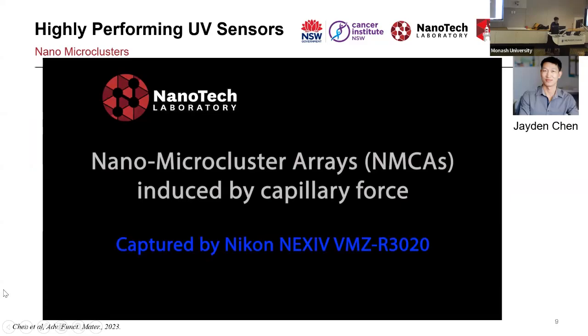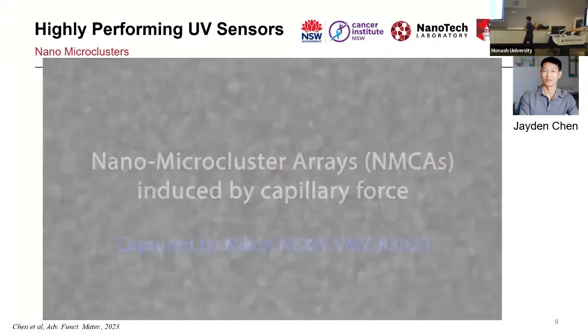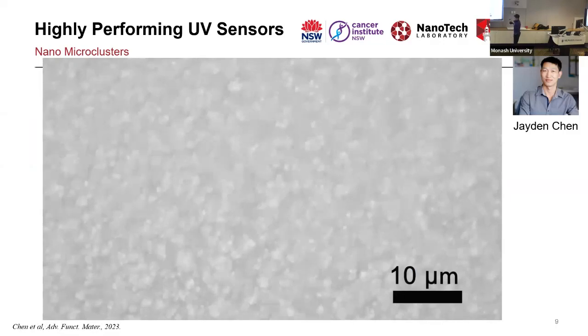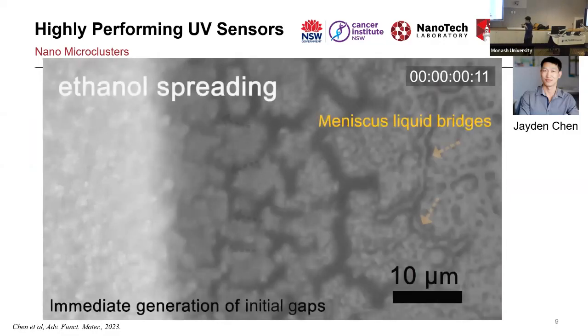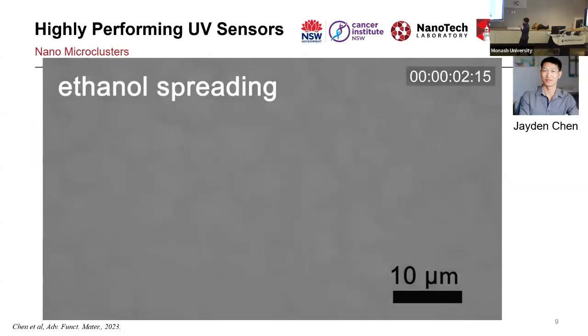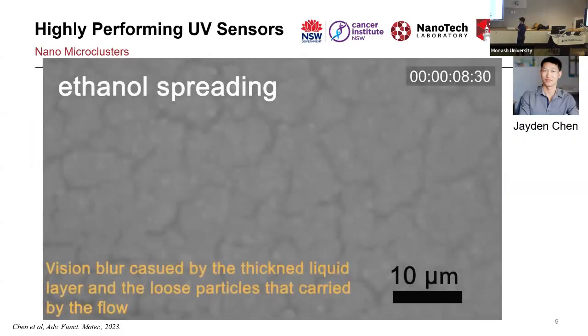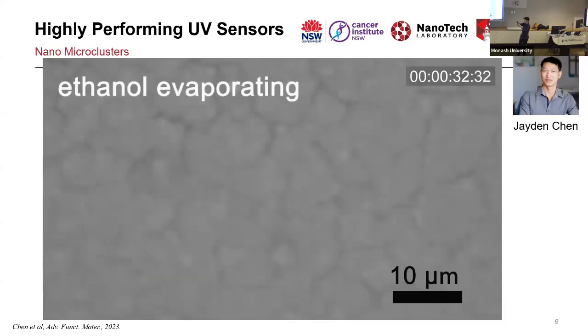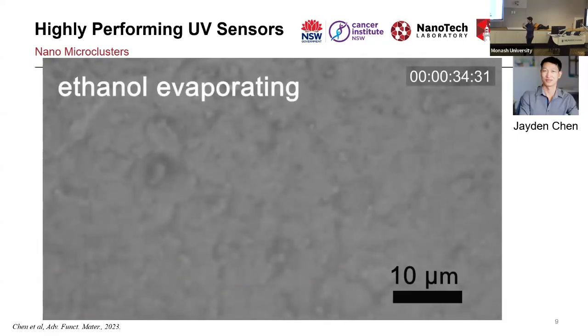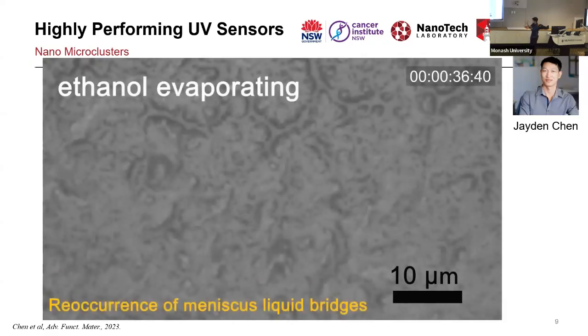So what I can show you is the video recorded under the microscope of how ethanol is actually changing the structure. What you see right now is the structure from the top view. And now the 5 microliter of ethanol is coming. First, it loses a little bit of focus because the film shrinks a little bit, from 18 micrometer down to maybe 16 micrometer. But now the ethanol is evaporating.